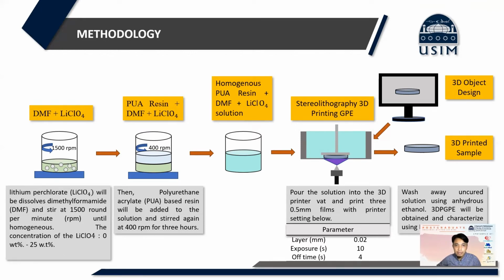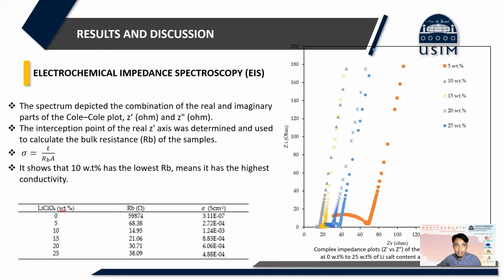Then the precursor will be poured into the 3D printer bed and printed into 0.5 mm films with this setting. Then after the printing process is completed, the polymer electrolyte will be rinsed using anhydrous ethanol to wash away uncured solution. Then the sample will be characterized. This is my result and discussion.